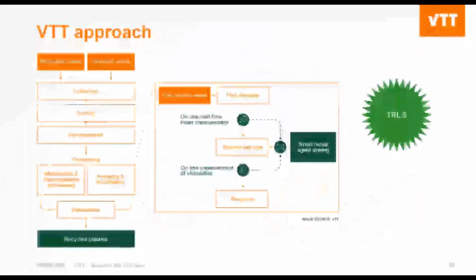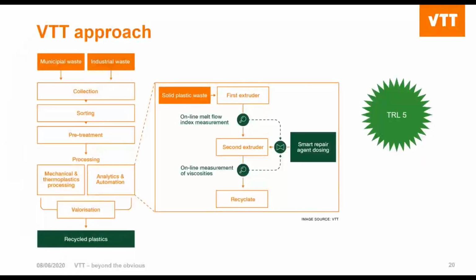At VTT, we use an approach which we would call smart recycling. What we do there is, after collection, sorting, and pre-treatment, which is done in a very traditional way, we reprocess the solid plastic waste through a first extruder. At the outlet of the first extruder, we measure the rheological properties of the polymer, feed it into a second extruder, and at the outlet of the second extruder, we measure the viscosity of the outcoming polymer melt. And all this information is fed into a controller, which can do several things.